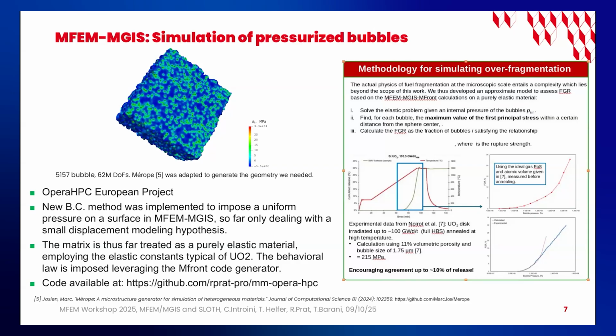So we have set up, in the context of a European project called OPERA-HPC, a simulation of those effects, and we were able to describe the progressive rupture of the matrix with a very simple model and try to correlate that with the experimental data. And I'm sorry, it's not quite readable, but you have the experimental data in blue, and at the very beginning of the annealing, we have a good correlation between the release of fission gas products, which comes from the cracking of the bubbles, and the experimental data. So a good correlation between simulation and experimental data.